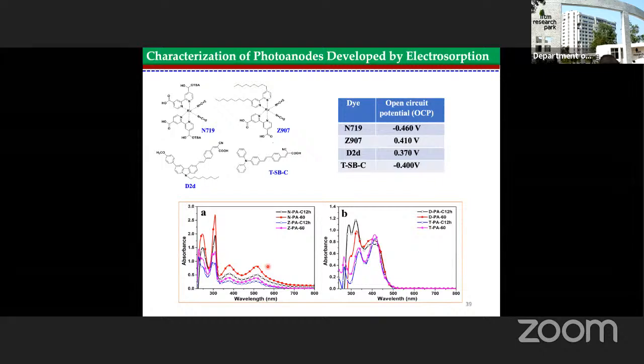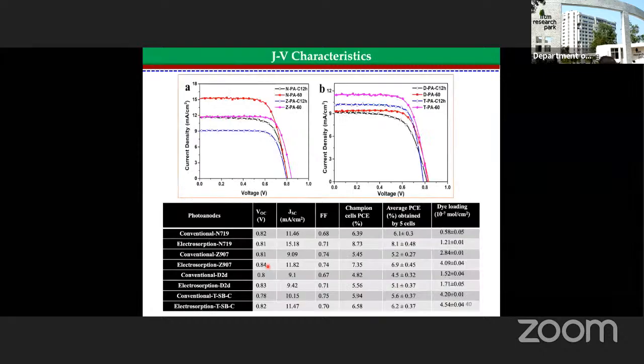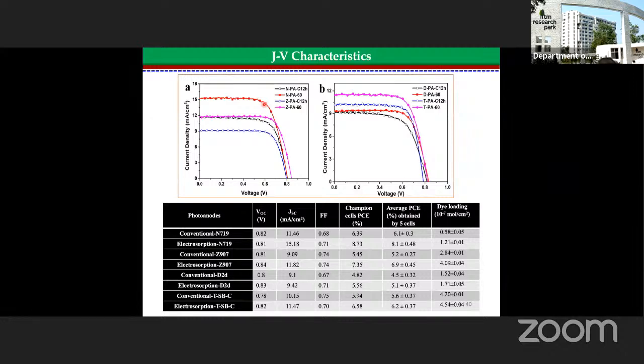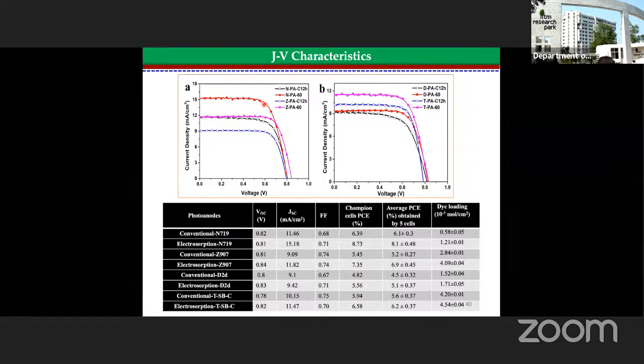So you can see this performance here. Compared to the black one, the red one has significantly improved performance in terms of JSC. That means the back electron transfer is kind of prevented because the VOC did not improve much, but JSC improved. So back electron transfer did not happen much when we use the electrosorption process, because that dictates how the dye absorbed and how much dye absorbed.